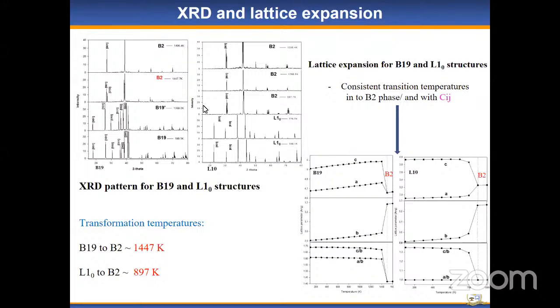So particularly here, I want to show that we can use the LAMMPS code to generate some XRD patterns, just to check on how the systems are transforming from one phase to the other by looking at how the peaks are changing. And this also gives us an opportunity to learn at what temperatures this particular system can change from one phase to the other. And we have done that successfully, and we found that for certain phases, B19 to B2 transformation occurs at high temperature, while the L10 is at a bit lower temperature. So these are capabilities that we are able to perform using the facilities at the CHPC.